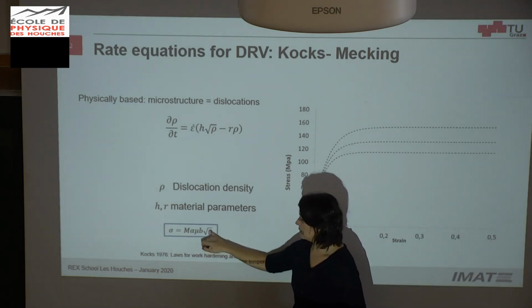First of all, here you have the dislocation density, which means that all dislocations produce the same strain field. This is telling us that dislocations are isolated, producing a strain field, and that's it. This is not taking into account dislocations at boundaries where the strain field is smaller, or forming dipoles.